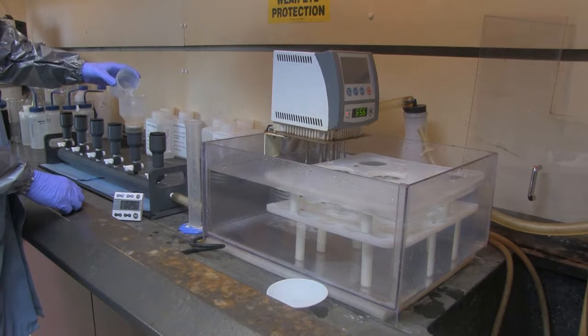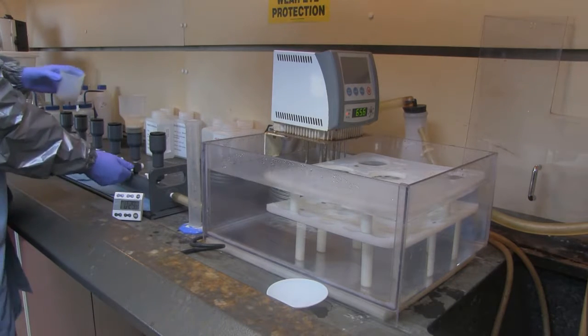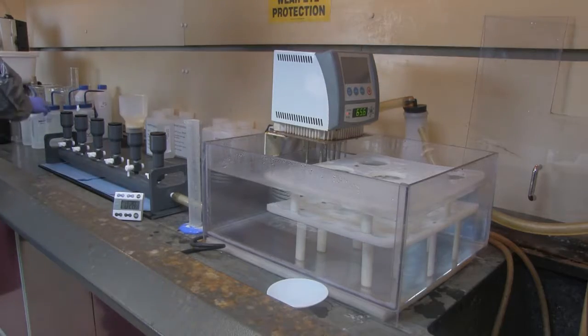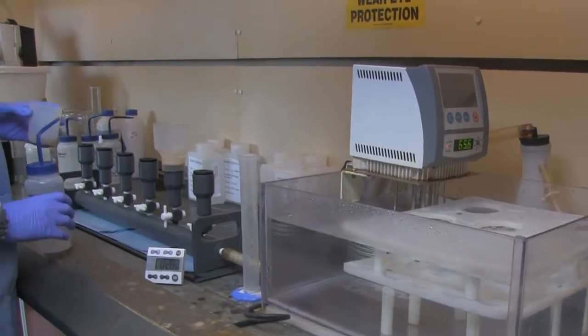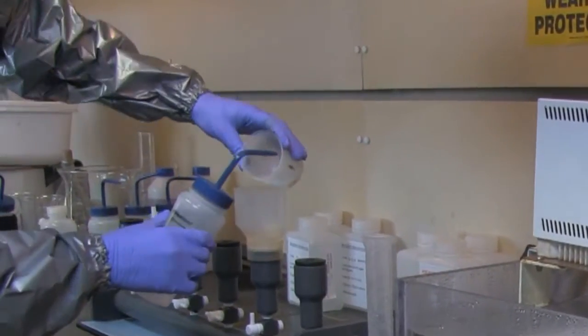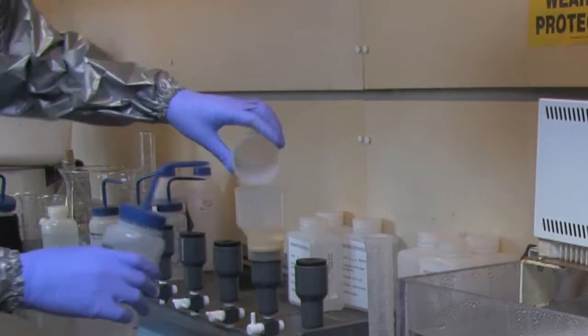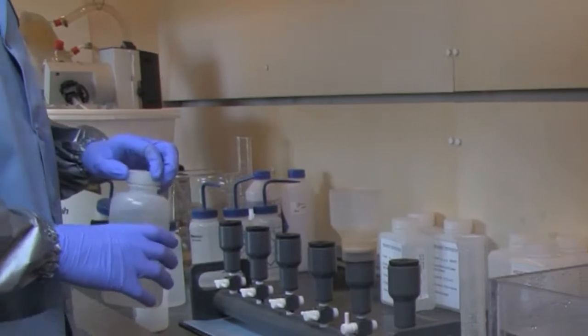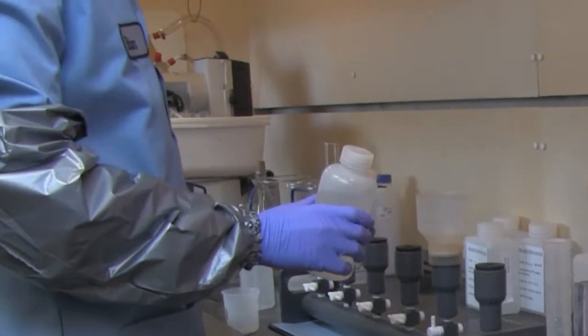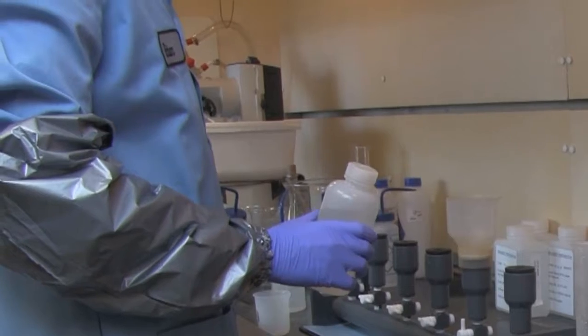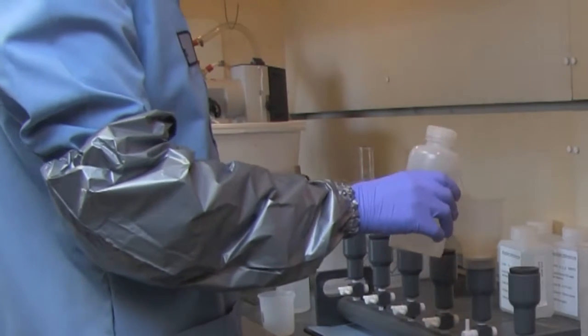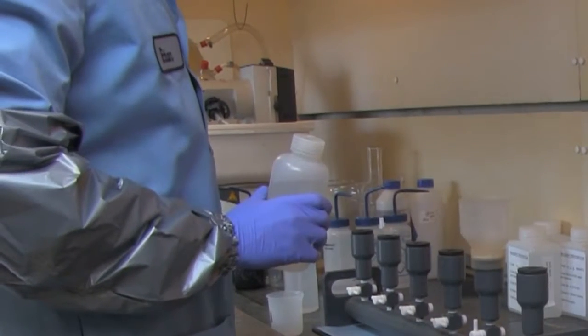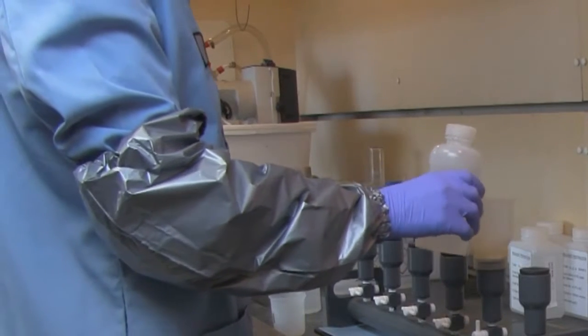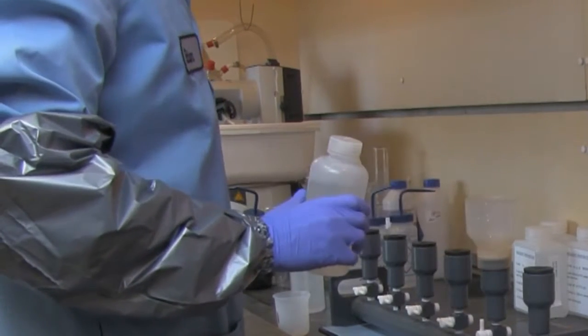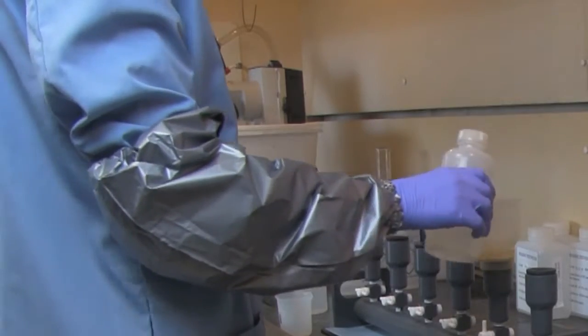Ethan's going to filter the sand and rinse the acid off of it. When it's completely filtered, he'll dry it and he'll weigh the sand again, and whatever weight was lost from his first weight till after the acid bath is the percentage acid solubility. There are specifications for proppant up to 30-50. Can't have more than 2% acid solubility. 40-70 is a 3% specification, and as of yet 100 mesh does not have a specification.